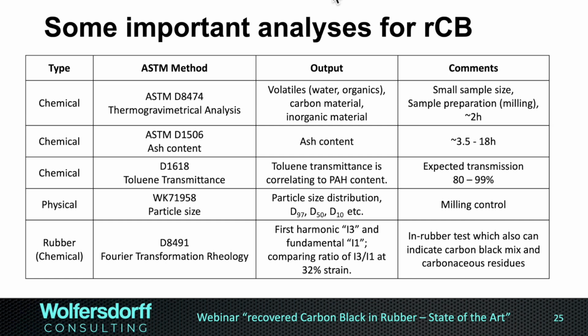Then we have the particle size distribution test, which also gives us the D97, D50, D10, everything we want to characterize all the colloidal, the physical particle properties. And we got the Fourier transformation rheology, which is an in-rubber test and indicates the carbon black mix and the carbonaceous residues.